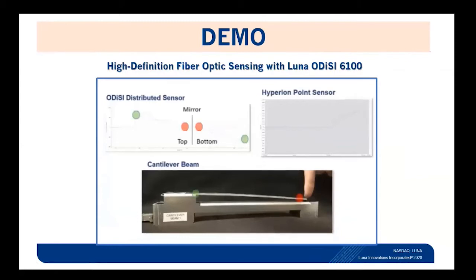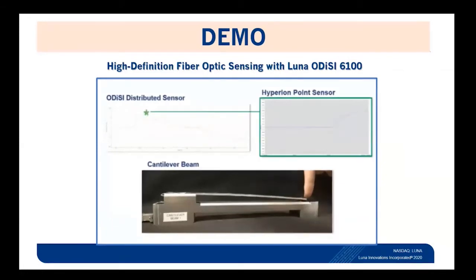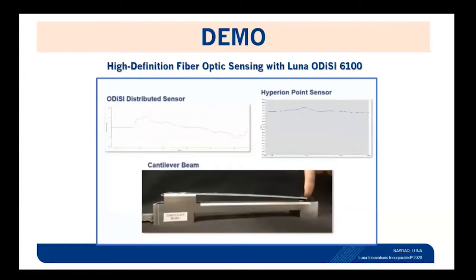On the left is from the ODiSI, so the high-definition sensing system, and you can see where those two notches are. There are stress concentrations that have been created, and they're mirrored on both the left and the right-hand side of the graph because the test sensor runs along the top and the bottom, so you have it in tension and compression. What you saw a second ago was that where the fiber Bragg grating is located, the data on the right lines up very well, or the same as the magnitude of what we're seeing from high definition on the left.